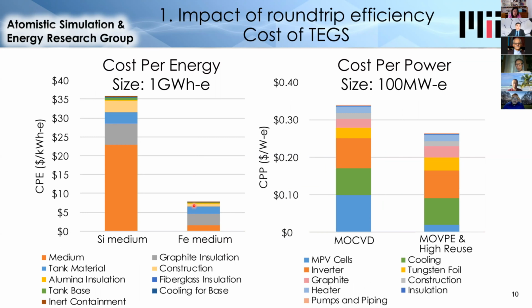The next bar shows a potential cost savings if the storage medium was changed from silicon to iron. And the reason this is cheaper is both because iron itself is inexpensive, but also because its volumetric energy density is higher, which means the rest of the system shrinks for the same amount of energy stored. The problem with iron is that it also reacts with carbon, the graphite tank, but it doesn't form a protective silicon carbide layer, and so this reaction would continue until failure. However, we wanted to investigate whether there's a mixture of silicon and iron that could be used, which would mean that there could be some cost between these two extremes.